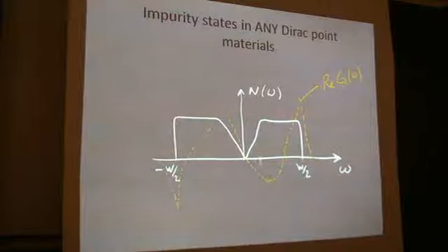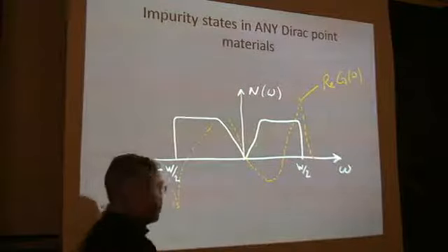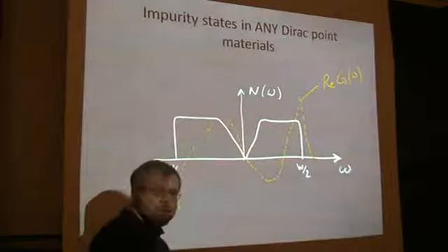And the real part is shown here with this dashed line, yellow. So every time I have a sharp edge in one of the Kramers-Kronig partners, the imaginary part, for instance, has a step, and the real part will have a peak, and it will have some bend here. And inside this notch, it will have this marginal Fermi liquid. The imaginary part goes like absolute value of omega, but the real part will go like omega log omega. For those of you who remember marginal Fermi liquid, so like susceptibility statements.